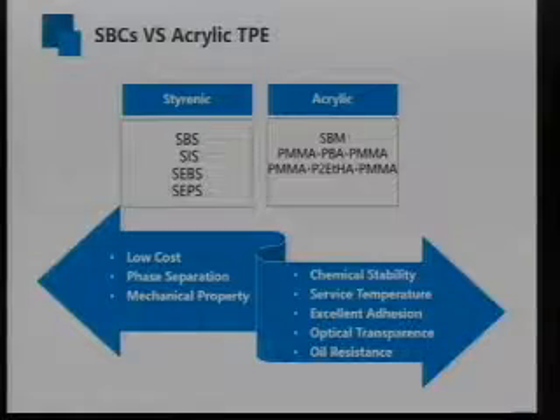However, the middle block composed of polyisoprene or polybutadiene has the vinyl group, which is vulnerable to oxidation and UV degradation. So it's not so chemically stable. Also, for the polystyrene, its glass transition temperature is only 100 degrees Celsius and it is miscible with the polydienes. This makes the upper service temperature always lower than 100 degrees Celsius, which is not so preferred in the industry. So, on the other hand, acrylate-based thermoplastic elastomers can get rid of all these problems because of the all saturated backbones. Also, acrylate-based thermoplastic elastomers can give us some extra bonus, including the excellent adhesion and good optical transparency and good oil resistance.